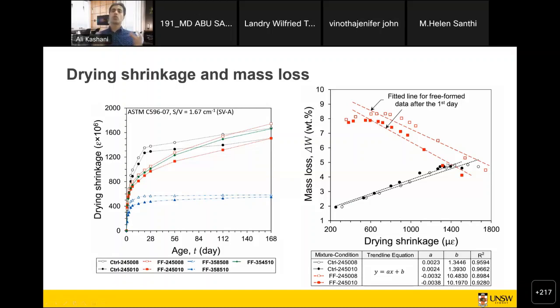Normally, for normal concrete, when drying shrinkage increases, you also have mass loss at the same time because the water is evaporating. But for the printing sample, you can see it's the opposite because it's very unhydrated. So it gets the moisture back, some hydration is happening, some of the product develops. You also have the carbonation shrinkage as well. Some of those unhydrated cement starts getting carbonated. And that's the reason that you got this kind of very unusual behavior for 3D printed samples in a free-form condition.